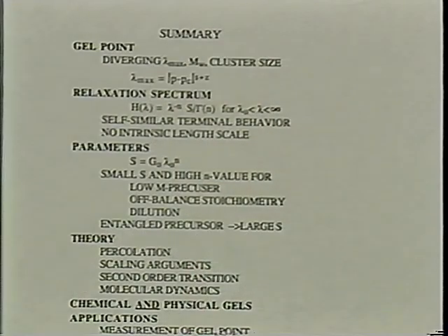For breaking a gel, we don't need many bond breakages. We did some estimates, but it's very, very low. So I'm not sure whether we can even detect that. We would need a very sensitive spectroscopic method to see small changes in those bonds occurring during flow. But that's still on the agenda, something we would like to find out quantitatively. We would like to know what's happening during the breaking of those gels. This sums up what I wanted to report concerning the chemical gelation.